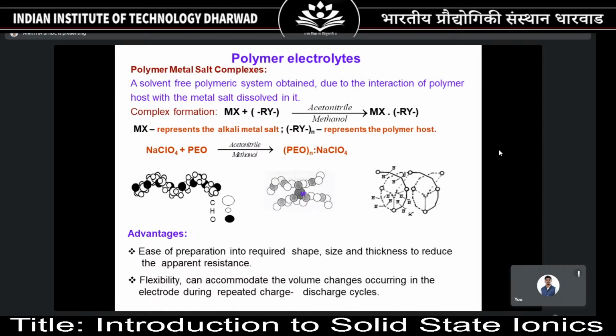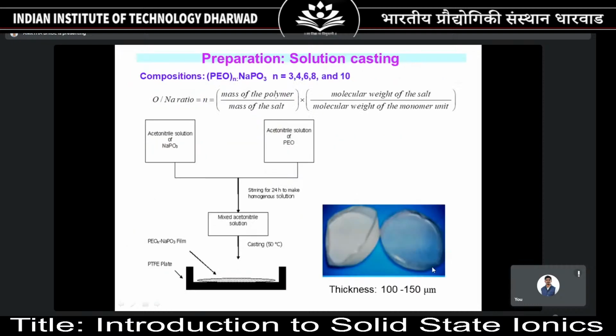electrochemical window. That's why people go for anhydrous acetonitrile or methanol, and you just mix the salt, get it dissolved in acetonitrile or methanol, and then you add the polymer and evaporate the acetonitrile or methanol. You end up with polymer electrolytes which are freestanding, which you can get with a thickness of roughly 100 to 150 micrometers. So this is how you get control over the thickness.